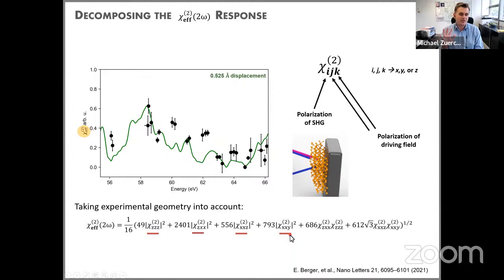So these are the 4 independent tensor elements in that system. And what we showed in our work is that if you know how your crystal is oriented, and you know what the electric field of your laser is, you can actually do all the tensor rotations and projection operations and determine how these different tensor elements project into your measurement. So what do you actually measure? What you measure is a combination of these 4 tensor elements weighted by these factors.